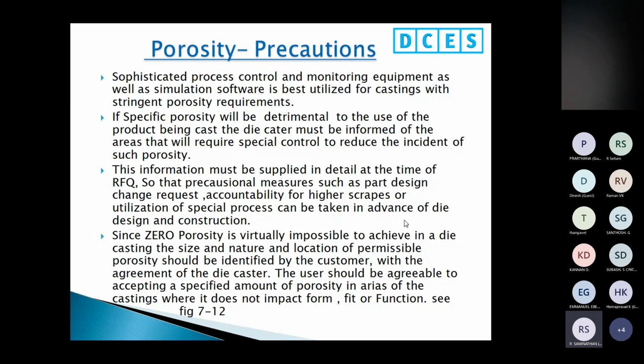If specific porosity will be detrimental to the use of the product being cast, the die caster must be informed of the area that will require special control to reduce the incidence of such porosity. Otherwise, the die caster should ask the customer. This information must be supplied in detail at the time of RFQ so that precautionary measures such as part design change request, accountability of the higher scrap, or utilization of a special process can be taken in advance of the die design and construction.